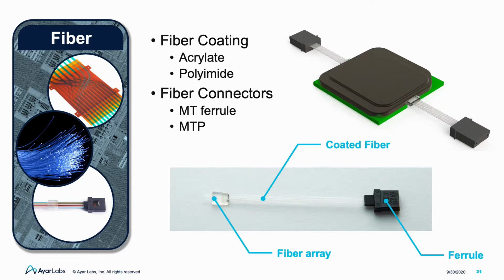Let's focus on the fiber components within the package. The fiber typically has a silicon dioxide cladding with a diameter of 125 microns. The core is a doped oxide with a diameter similar to that of the mode field diameter, again roughly 8.5 microns in diameter for the O band. The fiber is coated with a polymer which protects the silica fiber. For the purposes of this talk, it is the coating that is most interesting from a materials engineering perspective. The other consideration is the fiber ferrule and how to connect it to other ferrules.